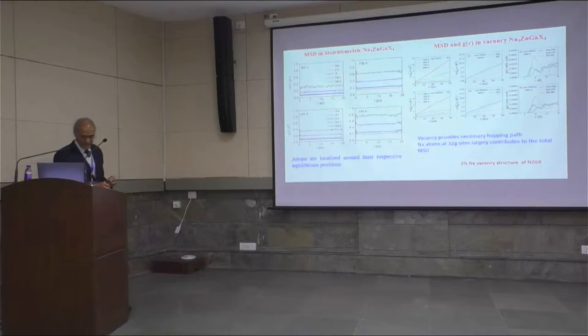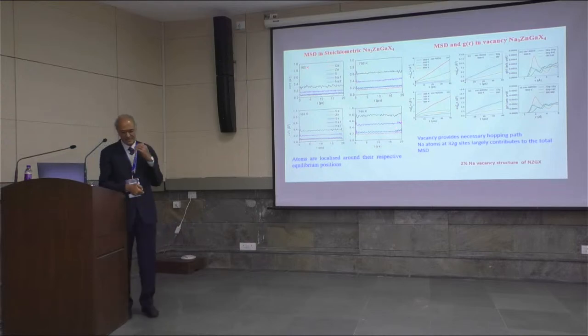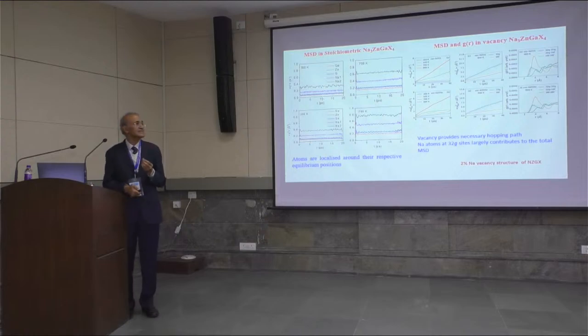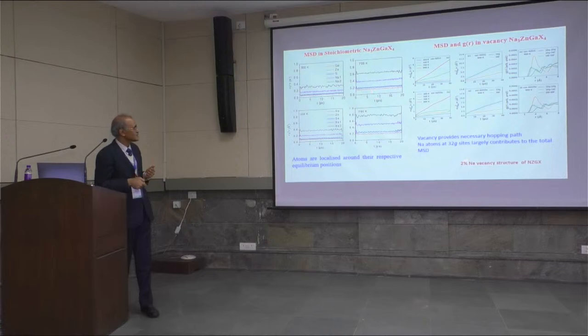So what do we see here now? In the real structure, the diffusion is helped by defects of various kinds. In a perfect crystalline structure, it is more difficult. So we have introduced some small vacancies, and that allows us to identify the diffusion, which you can see from how the mean square displacement increases with time. If you just look at this, you may feel it is liquid-like, but really it is not liquid-like, but strongly influenced by the underlying lattice.